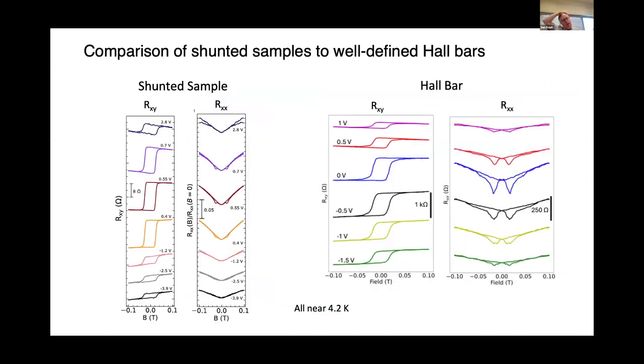So about 2 years ago, we first published some devices where we hadn't figured out how to make these Hall bars yet. So we just had stacks in which we had a little piece of the magnet with a larger piece of the topological insulator on top, and we're measuring the Hall resistance and the longitudinal resistance. We knew those devices were highly shunted because there were current paths for the current to flow through the topological insulator that weren't in contact with the magnetic layer.